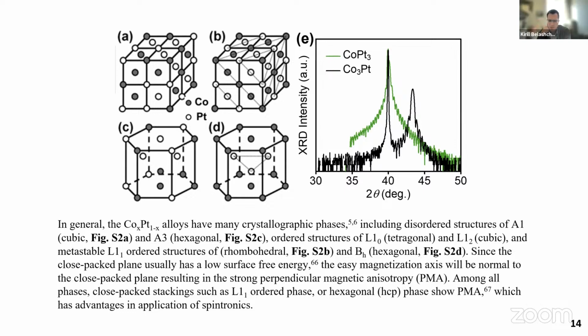But those correspond to different concentrations, right? At 50%, the thermodynamic equilibrium phase is L10. There are also some reports of L11 in thin films, which is surprising. But do you see any specific evidence of these?